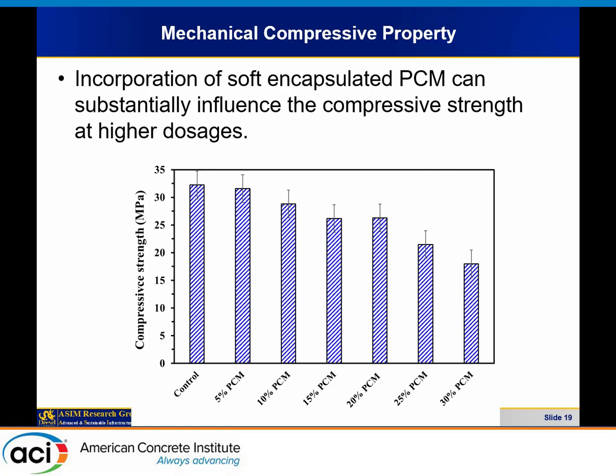If you look at the mechanical properties, this is the question that everybody asks. When I go to give a talk, everybody asks, what would be the effect of adding these soft materials on mechanical properties? So this is the control, and here we are increasing the dosage. Compressive strength: if this is the control, we have to be very careful. 50% reduction by adding 30% by volume. And this is 30% of the aggregate, not the entire concrete. So we replace 30% of the aggregate, and we get about a 50% reduction for the entire concrete. So we have to be very careful. So there is some trade-off here.